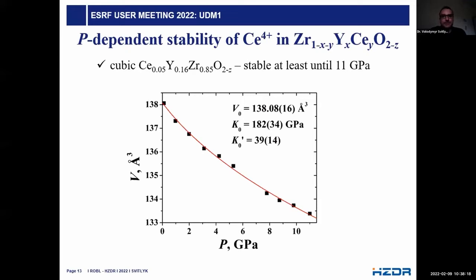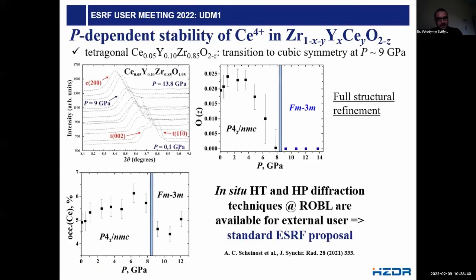One example is the cubic yttrium stabilized cerium doped phase, and another one is a tetragonal phase. Well, the cubic phase remained stable up to the maximum studied pressure of 11 GPa. So it's quite boring from a scientific point of view. Nothing happened at all, but it's good from the point of view of stability. Things were more interesting with the tetragonal phase. In fact, we did observe a transition around 9 GPa from the tetragonal to a cubic modification.